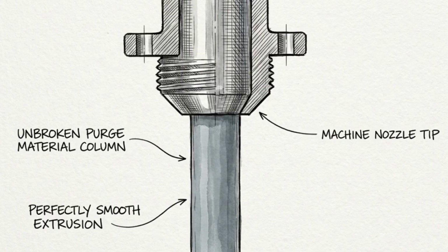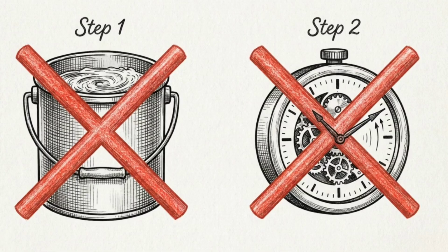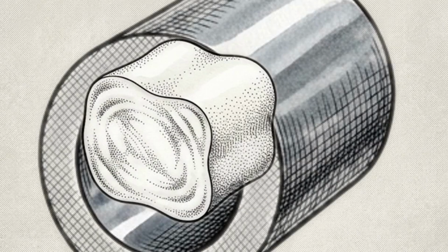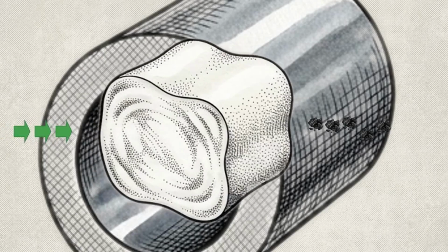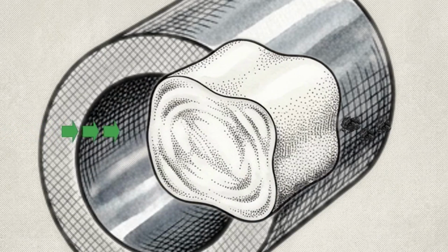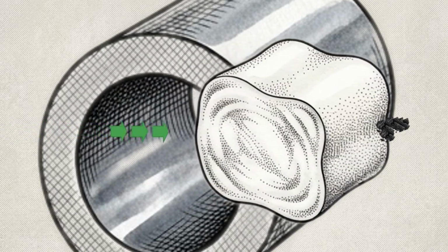Step 2. Feed the purge continuously so it moves through the machine as an unbroken plug. There are 2 specific errors to avoid. First, never mix or dilute a mechanical purge with carrier resin. Dilution spreads contamination rather than removing it. Second, do not let the purge soak in the barrel. Mechanical purges require constant forward physical movement to maintain their scrubbing friction.